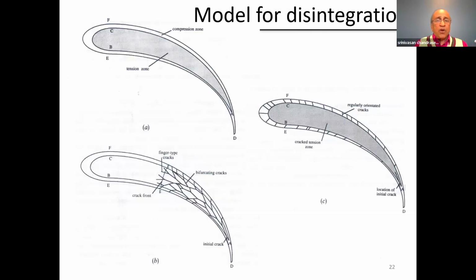Okay, now coming to reconstruct the picture of why this thing fragments. Here I'm showing schematics. So we have a drop in A. The interior of the drop is in tension and the outside is in compression because of the way the drop has been quenched in liquid. And then we set a crack in motion in figure B at the tail. And so what happens is the crack picks up speed because it's feeding energy from the tensile stresses in the core of the drop. They are feeding strain energy. So the crack is well fed by energy, so it picks up speed. When it reaches the critical speed of 1600 or 1700 meters per second, it runs into this bifurcation threshold, so it splits.